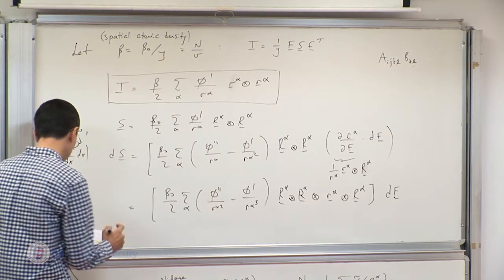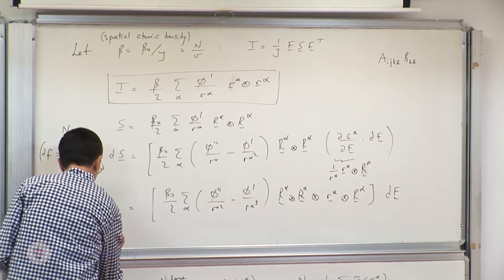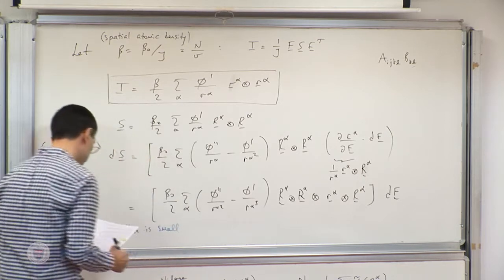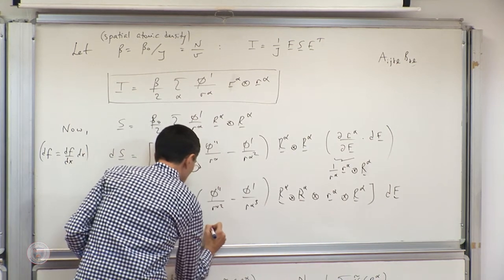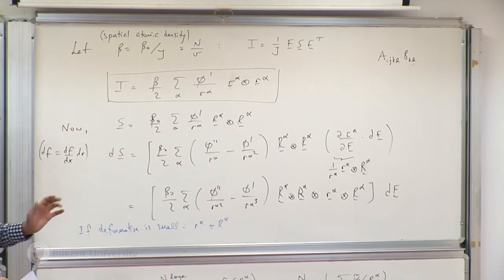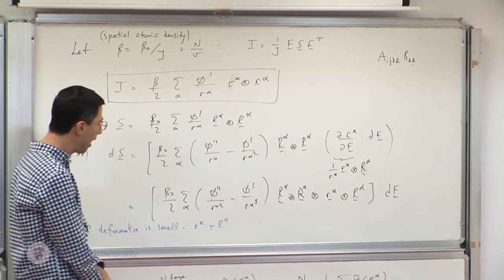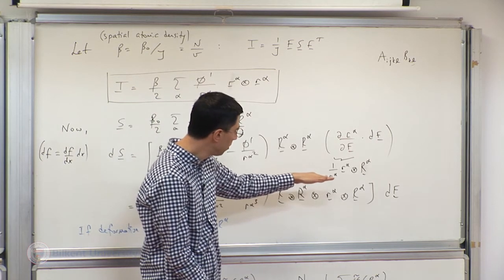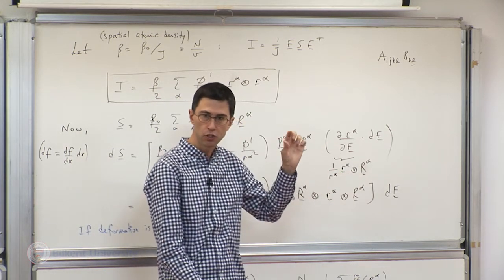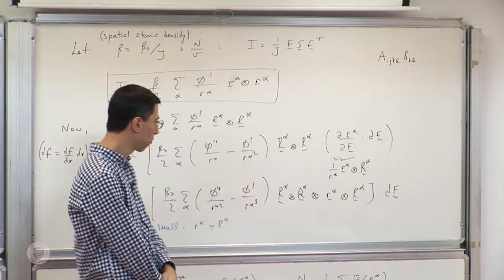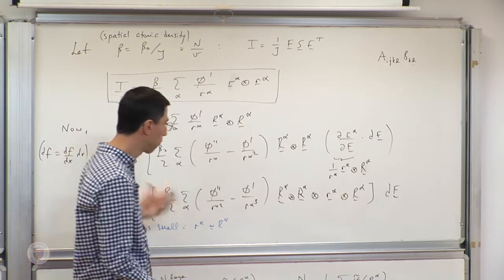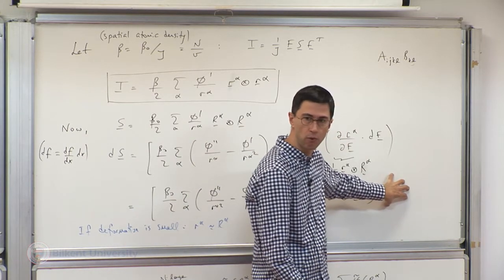We have a very important quantity in those brackets as our fourth-order tensor. To make it more apparent, let me simplify further by assuming now that the deformation is small — so the distance between atoms does not change appreciably — and retain in dS only what is linear with respect to that change.